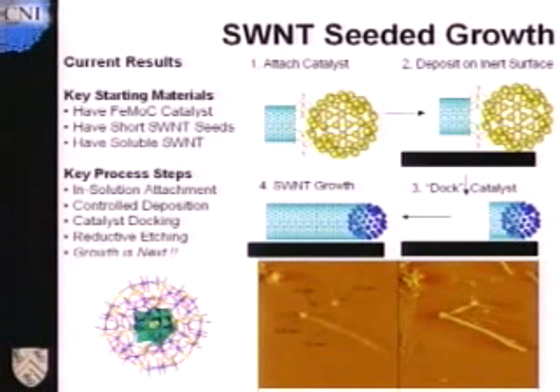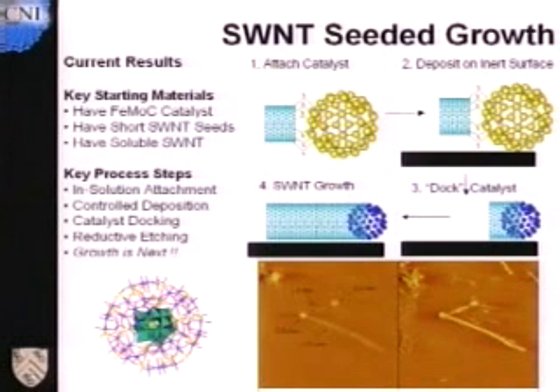Then we'll take a chemically defined catalyst particle and attach it here in solution. Now, the chemical that we're using these days is what we call FEMOC. It's kind of a nickname for a 114 metal atom cluster that self-assembles out of solution. It has 30 iron atoms, the balance molybdenum atoms, bound together by oxygens and a few acetates and a phosphorus atom in the center.